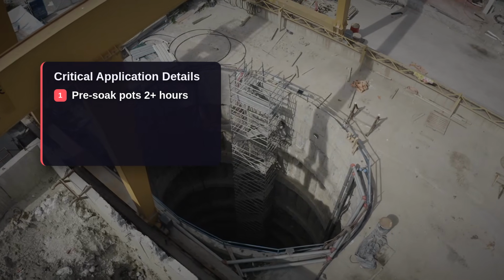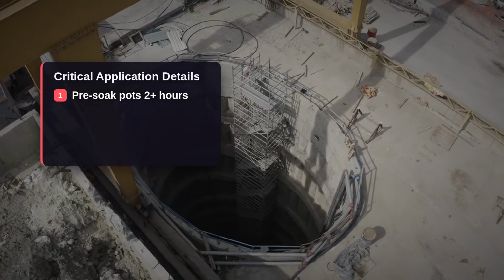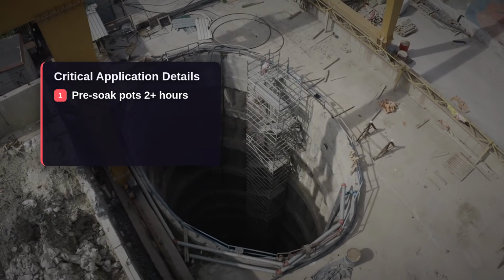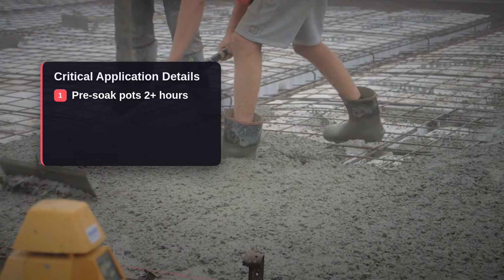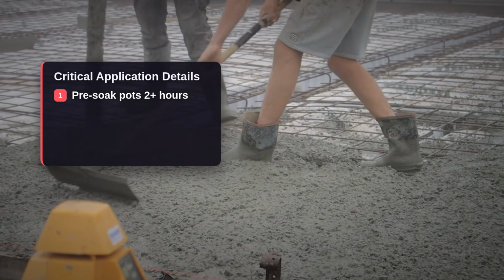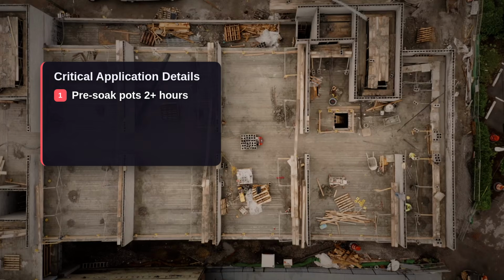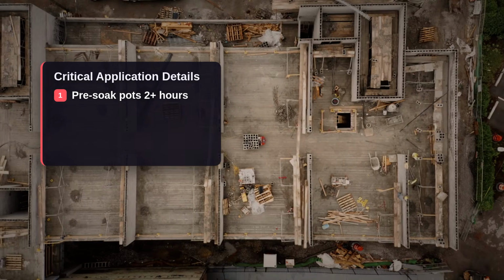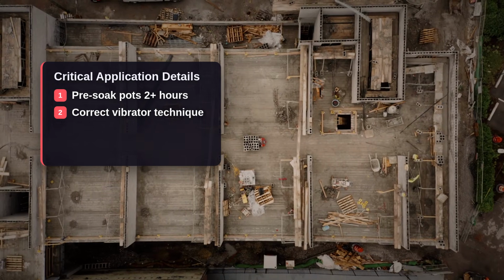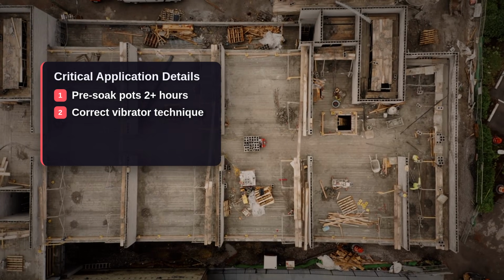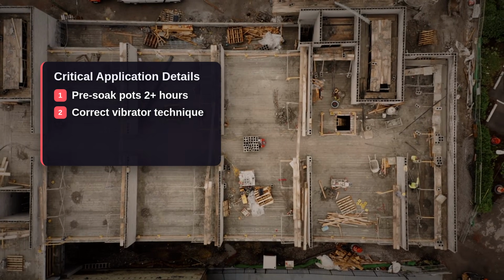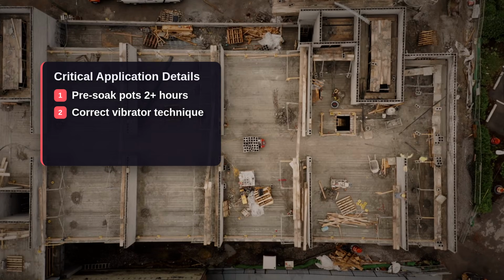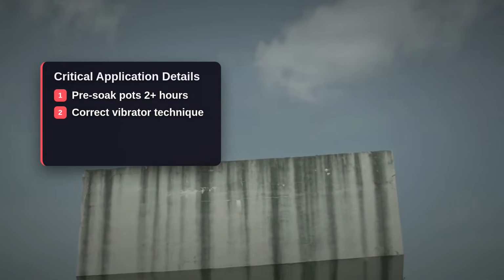The second common failure is incorrect concrete vibration during the pour. A filler slab requires a concrete vibrator to consolidate the mix around and between the pots. You need to eliminate air pockets in the structural concrete, not in the pots. The vibrator must never contact a clay pot directly. Direct contact transmits enough energy to crack or shatter the pot. You'll hear a dull pop, and you've just collapsed a void that was supposed to be there.